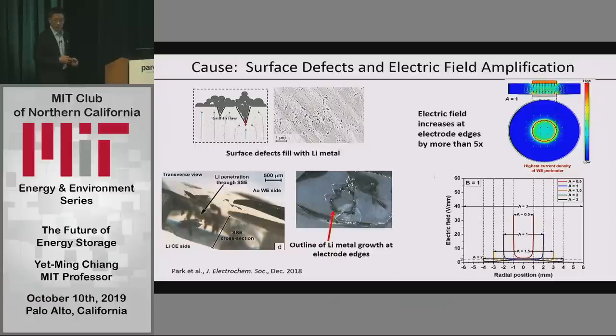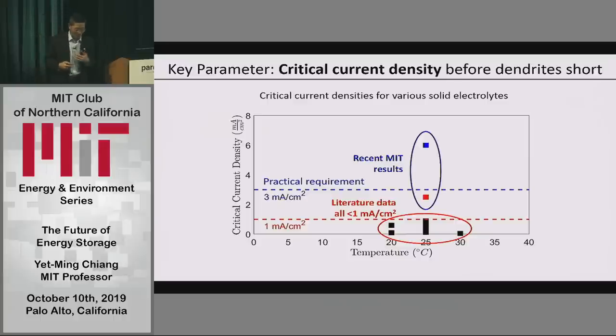We are making some progress on this. So to folks like us, what is success? It turns out that because of the phenomena that I just showed you, there's only a limited current density that we can run through these batteries before the metal dendrite forms and causes an internal short circuit. Today, that current density is too low on the vertical axis here. These are units of milliamps per centimeter squared. This is the current density through the battery. And it turns out that for a range of solid electrolytes, it's all below one. A practical battery has to be at least three.